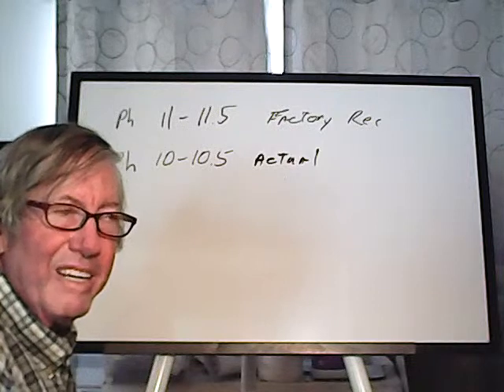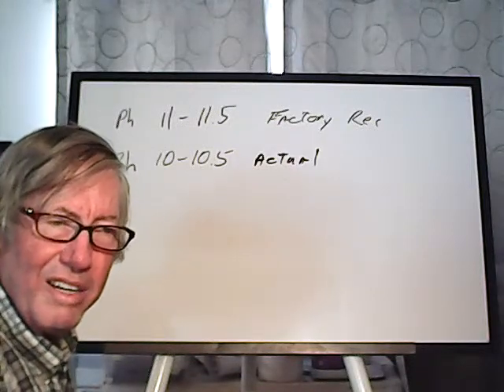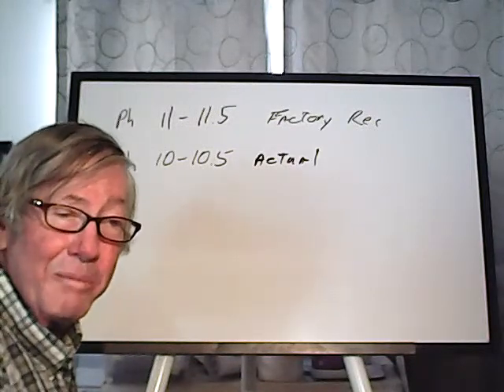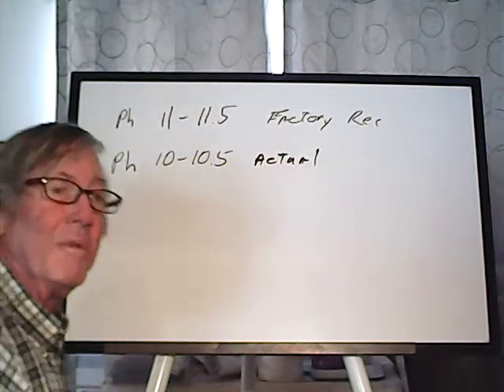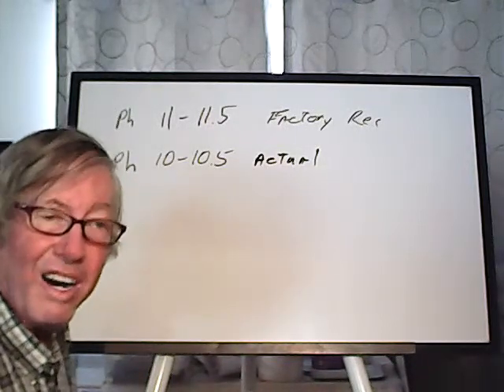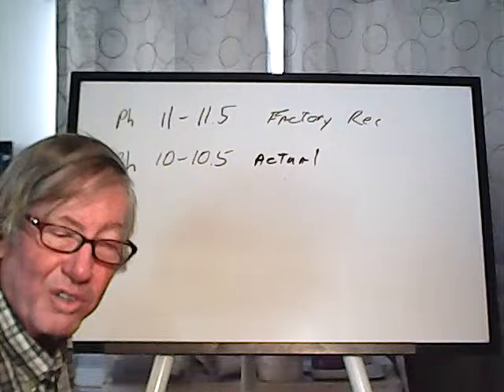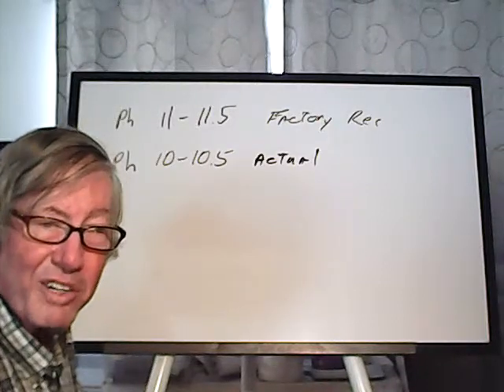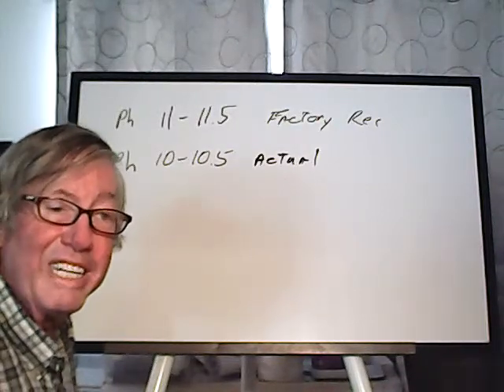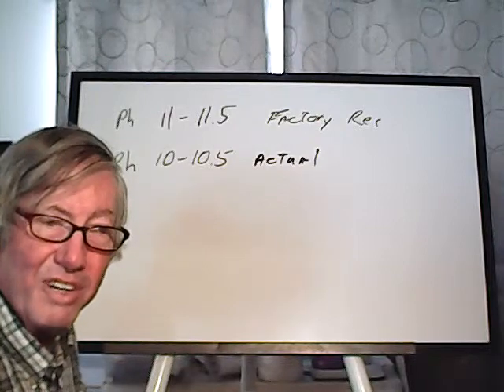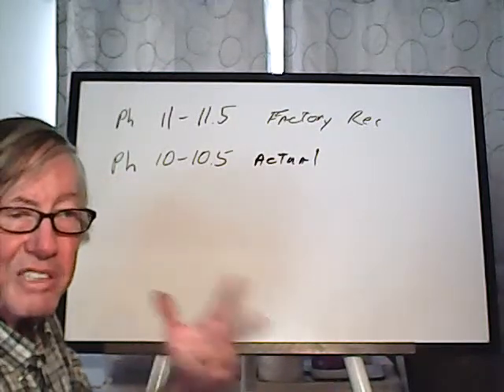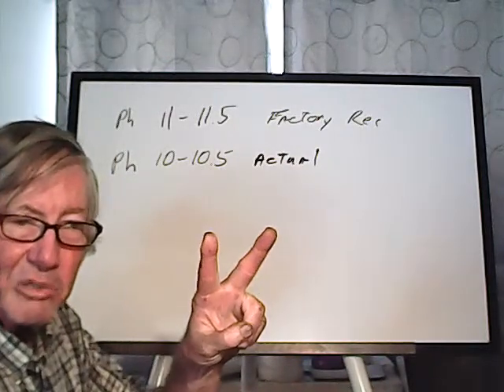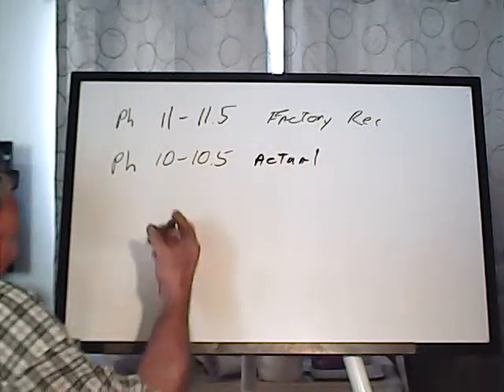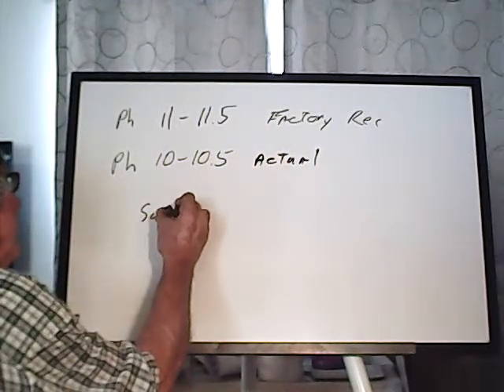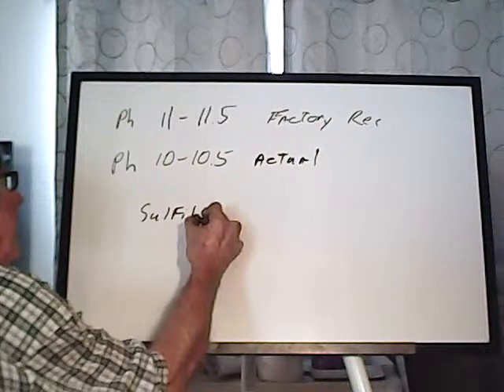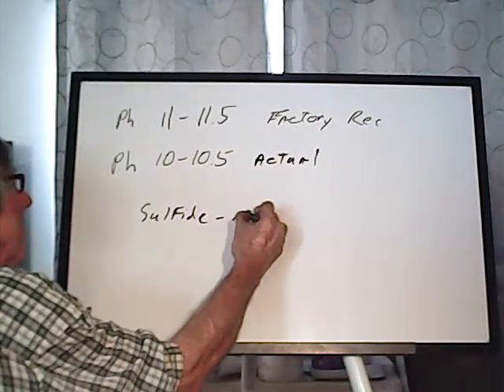It is not desirable because it's going to tend to be acid. It would be best to oxidize those sulfides first. You're going to get better recoveries. You could probably get reasonable recoveries from a sulfide ore if 2 conditions were met. Number 1, if your gold was not encapsulated in the sulfide.